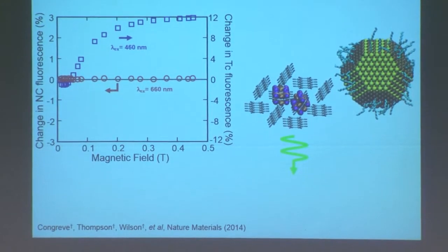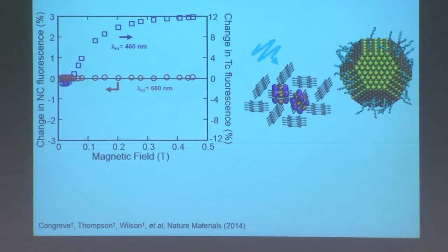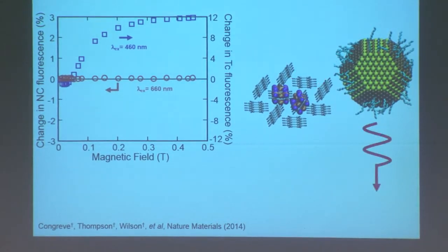And then as our experiment, we can excite the tetracene and monitor the fluorescence from the dot after it's transferred. This will tell us definitively what channel it's coming from. If it's positive again, we know we're just getting singlet transfer. If it's negative, we'll know we're getting triplet transfer. And I've kind of given away the answer by the way I've set up my axes here, but obviously it ended up being negative. So this was an independent verification that we're dumping triplets and not singlets into the dot.